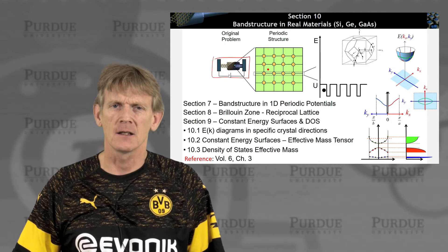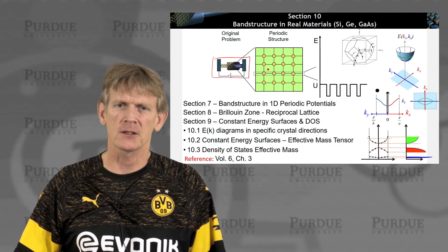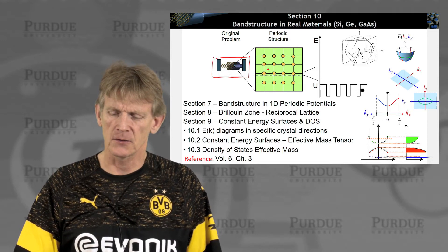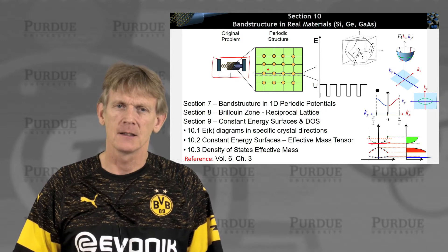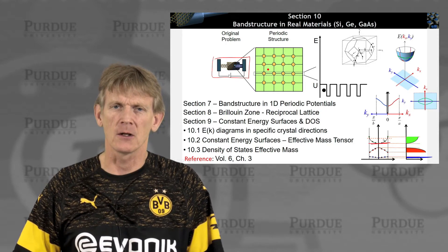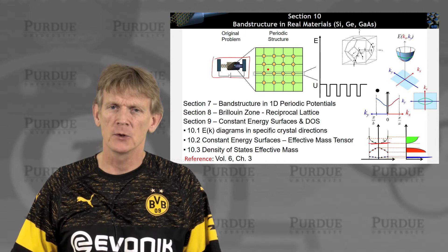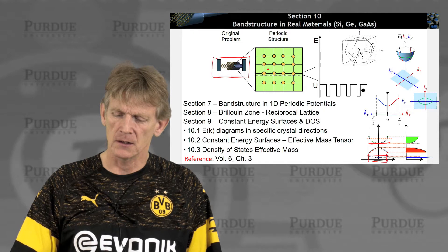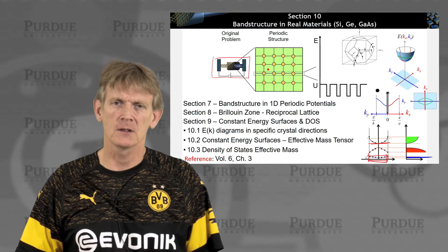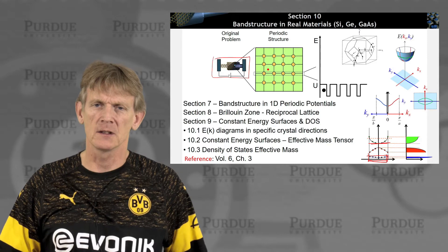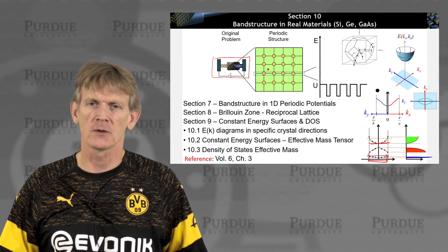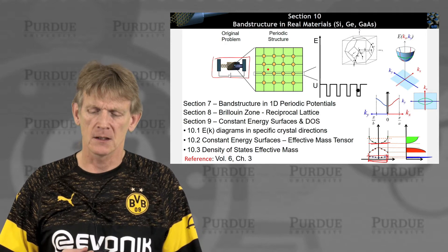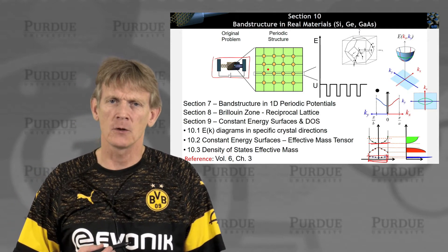We had calculated a 1D band structure previously, where we wanted to look at bands where electrons can transport through a structure and assign an effective mass, so they almost moved freely. We defined a Brillouin zone in which electron states are completely described. We didn't have to describe it with an infinite amount of crystal points, but we could collapse all of that property into a Brillouin zone.